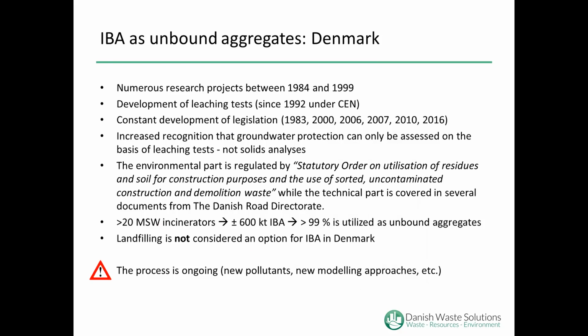Since then, there have been numerous projects carried out. Leaching tests have been developed. Legislation has been constantly developed and updated. People realized that in order to assess the risk for the groundwater, one needs to rely on the results of leaching tests and not on the results of the solid analysis. Today, the environmental part of the utilization process is regulated by a statutory order, while the technical part, meaning how to build from bottom ash, is covered in several documents from the Danish Road Directorate.